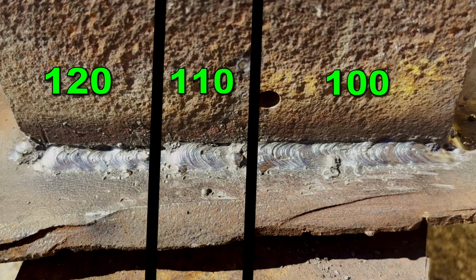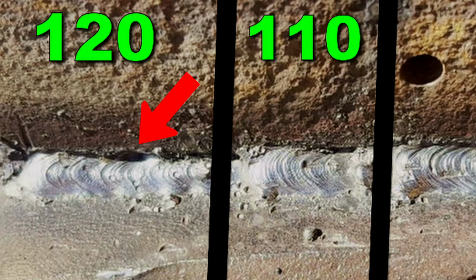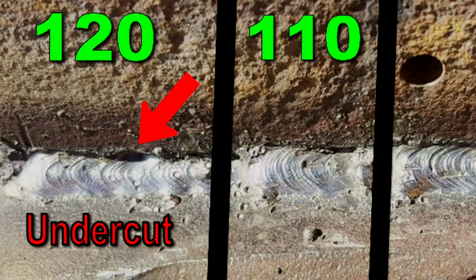Alright, so that weld's looking a little rough while we were playing with the settings, but that's perfect because now I'm going to go over a few common defects to look out for, and I'll show you how to fix it. If we look closely at the 120 amp weld, you can see we have some deep undercut. An undercut is when high amps leave a groove in the base metal that isn't filled in by the weld bead. This makes the weld more susceptible to cracking over time.